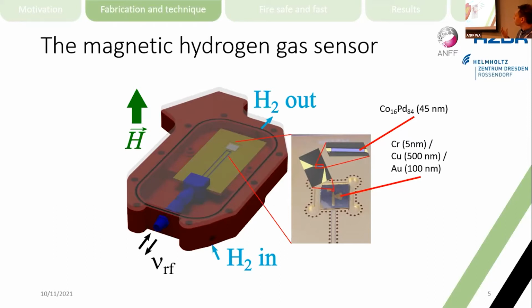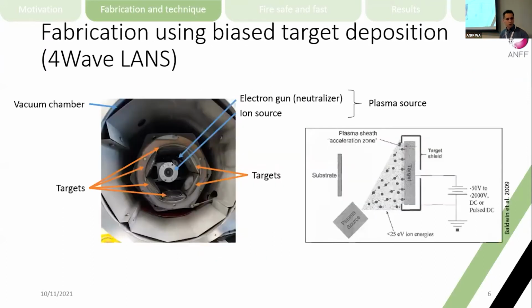Basically, when this cobalt palladium is exposed to hydrogen, its magnetic properties change. So that's why we call it the magnetic hydrogen gas sensor. In the alloy, the cobalt is responsible for the magnetic response, while the palladium makes it sensitive to hydrogen. And because the composition is so important for this alloy to work, I want to talk about fabrication and how we fabricate this alloy. We use a technique called bias target deposition, and we have equipment at the WA node of ANFF to use this bias target deposition, and that machine is called 4-wave.